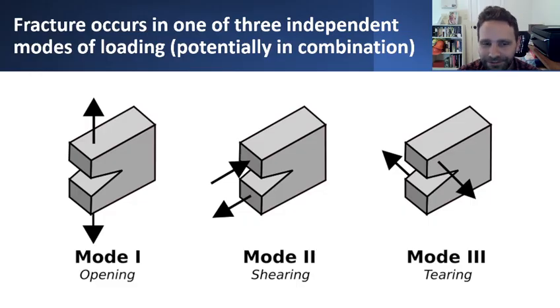And these three different modes of fracture fully encompass all the possible ways in which a crack might propagate and the resulting stresses that would develop around the crack tip. So as long as you can characterize what's happening in each of these three distinct modes of fracture and deformation local to the crack tip, you basically characterize everything there is to know about at least the stress field local to the crack tip.